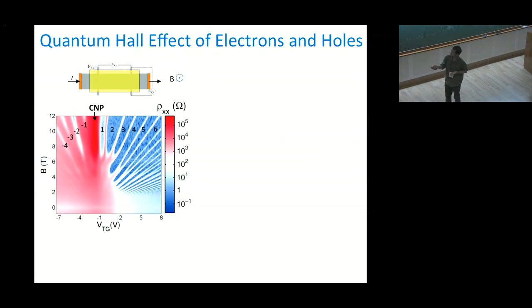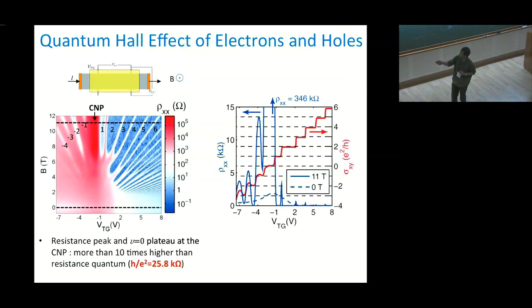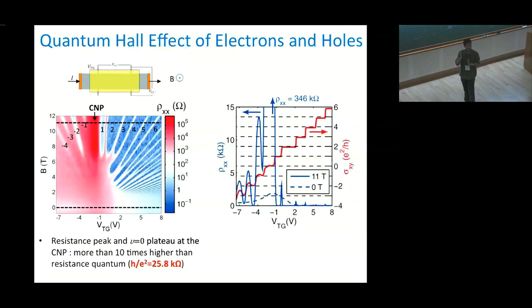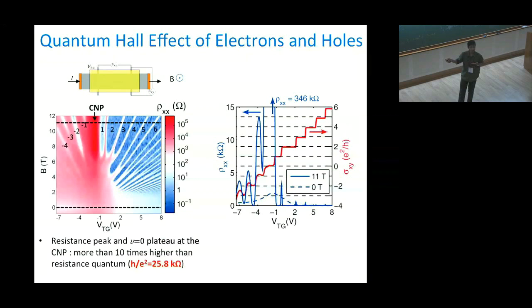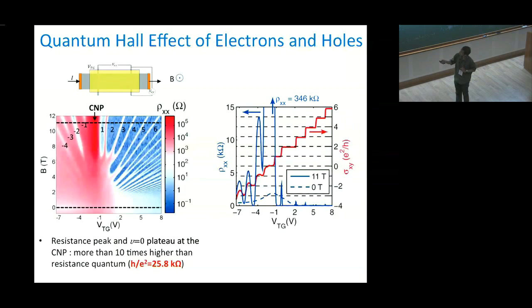Taking a cut at 11 Tesla of magnetic field, the blue line corresponds to longitudinal resistivity showing nice Landau level transition features on both the electron and hole sides. The red line corresponds to Hall conductivity, which shows nice quantum Hall steps. But the interesting thing happens at the charge neutrality point, where the total density goes to zero — the longitudinal resistivity goes very high, about 346 kilo-ohm, which is roughly 10 to 15 times higher than the resistance quantum. Any resistance higher than h/e² in the quantum Hall state is surprising.